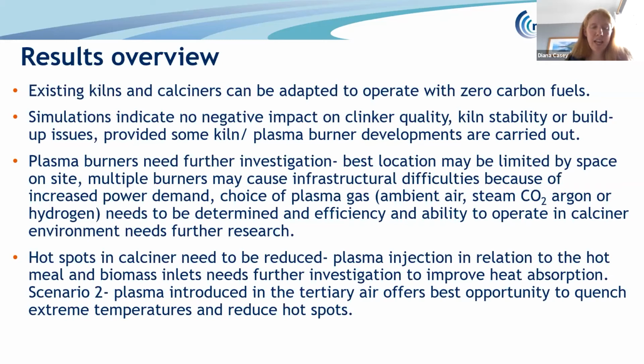The flame high temperature in the kiln can be tolerated with some optimization of the burner, both in terms of its design, so how it's injecting that fuel in, but also its location, just to try and maybe fire the particles at a slightly different angle so they don't quite reach into the bed possibly. Now, the best locations for the plasma burners going into the calciner may be limited by space on site, and things like using multiple burners might cause infrastructural difficulties because of increased power demand. And the choice of plasma gas, so you can use things like ambient air, steam, CO2, argon, or hydrogen, still needs to be determined. And the efficiency and ability to operate that plasma burner in a dusty calciner environment needs further research.